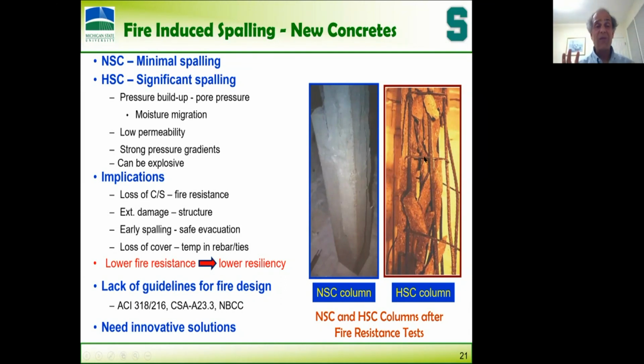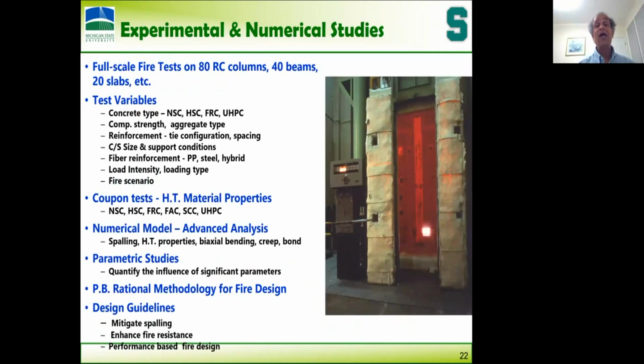So why this spalling happens is buildup of pore pressure. When it's exposed to fire, moisture becomes vapor. In normal concrete it can easily get out, 10 to the power of minus 16 is the permeability. When you reduce it by 100 to 1000 times, to 10 to the power of minus 18, that pore pressure converts into tensile stress and pushes the concrete out. So boom, boom, boom, throughout this fire scenario, you will have spalling. And this spalling can reduce fire resistance significantly.